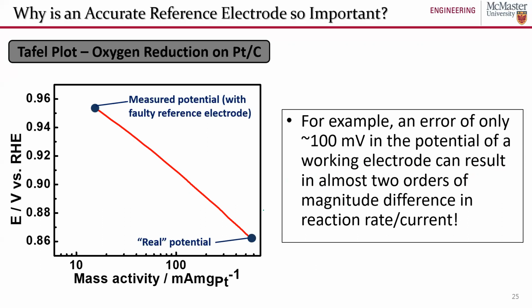Now, in case you have not gotten sick of me saying how important a good reference electrode is, I'll just provide a real example of why a reliable reference electrode is important. Let's take, for example, the case of oxygen reduction on carbon-supported platinum. Platinum is a very good oxygen reduction catalyst. And say we have a reference electrode that is 100 millivolts off from where we think it is. What can happen then with a 100 millivolt difference between the measured potential and the real potential of our reference electrode? We can have almost a 2 orders of magnitude difference in the currents that one would expect.